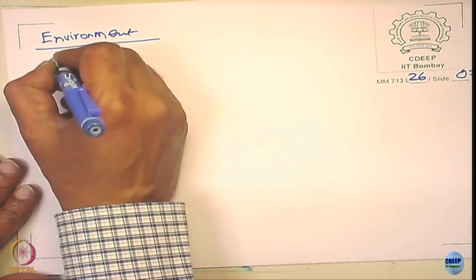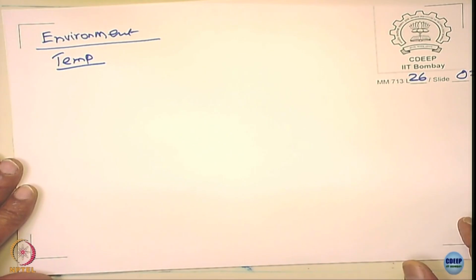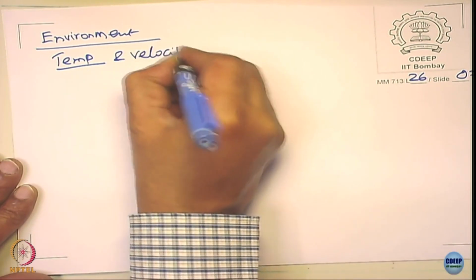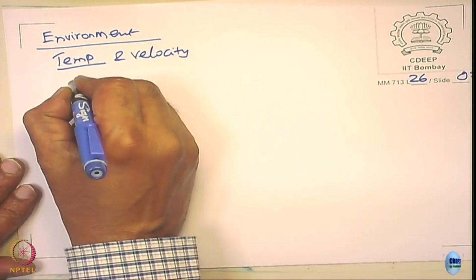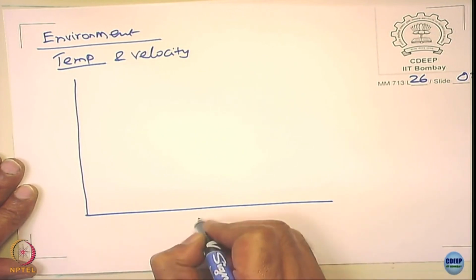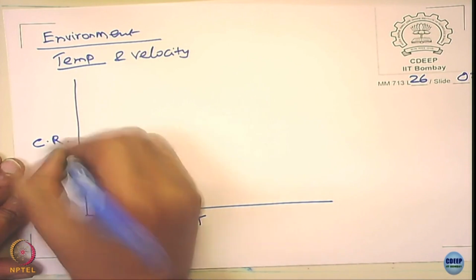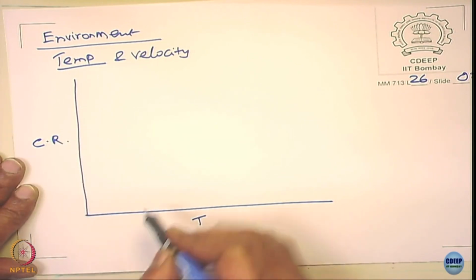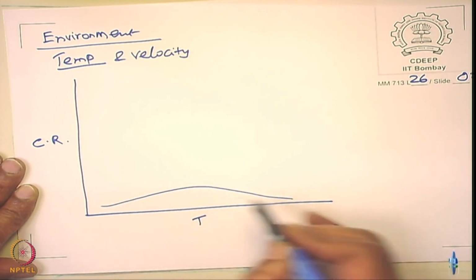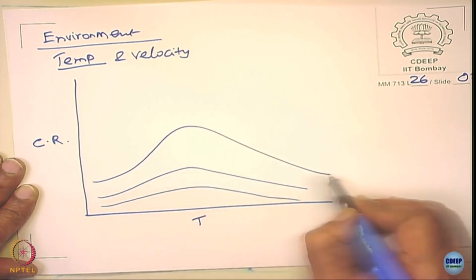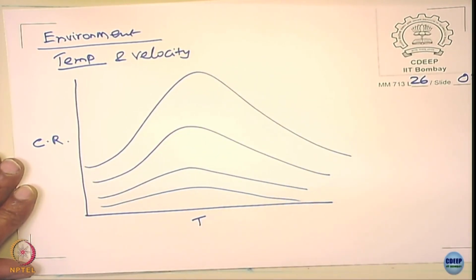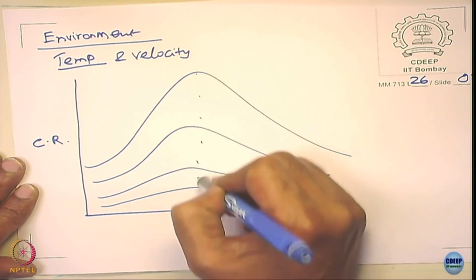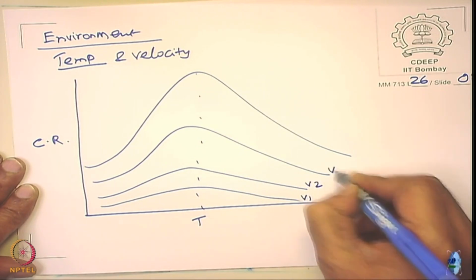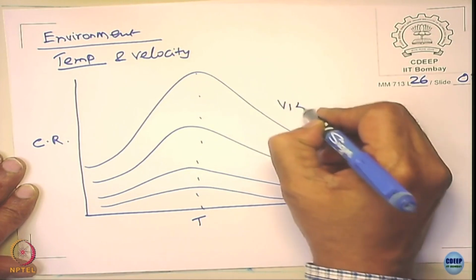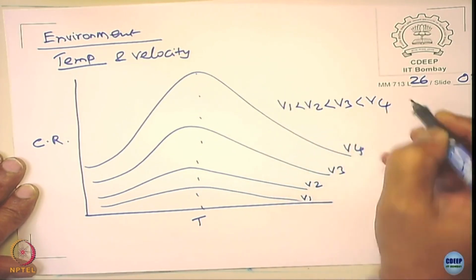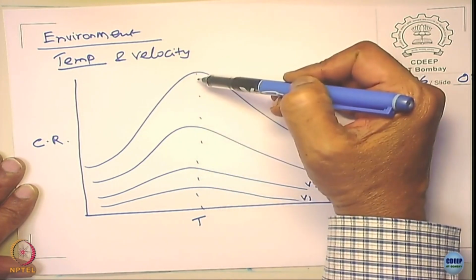First, the temperature, and the velocity. These two are very critical. So plot temperature versus the corrosion rate. You will find a curve like this. And very interestingly, in this temperature range, these are different velocities, V1, V2, V3 and V4, where V1 is smaller than V2, smaller than V3, smaller than V4. When the velocity increases, the flow assisted corrosion increases, but notice here,